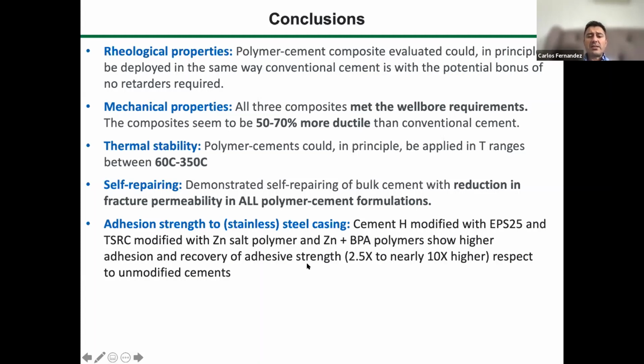Adhesive strength to stainless steel: there were two formulations for cement H. EPS 25 is the only one that brings about similar original adhesive strength, but higher recovery of the adhesive strength. And for thermal shock resistant cement, the cements based on calcium silicate aluminates, the zinc salt and zinc salt BPA polymers not only increase the original adhesive strength of the material compared to the unmodified cement, but also the recovery ratios are between 2.5 and 10 times higher than the unmodified cement. This is just some information for a 15 minute talk. Obviously, I can answer any questions you may have.